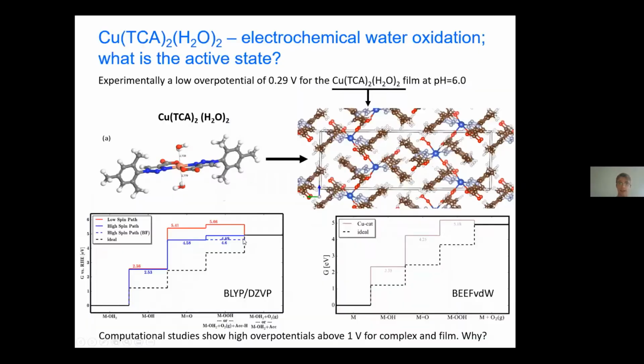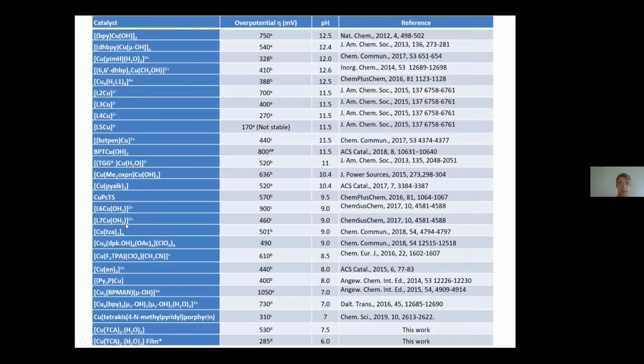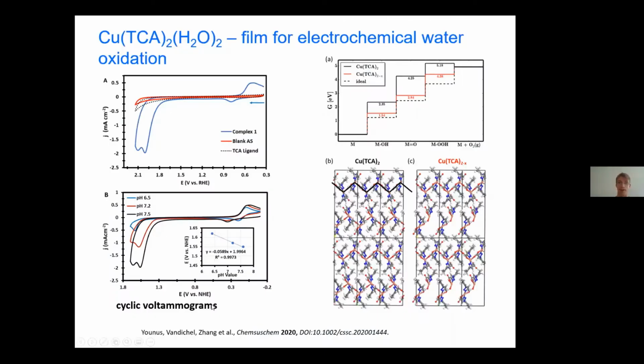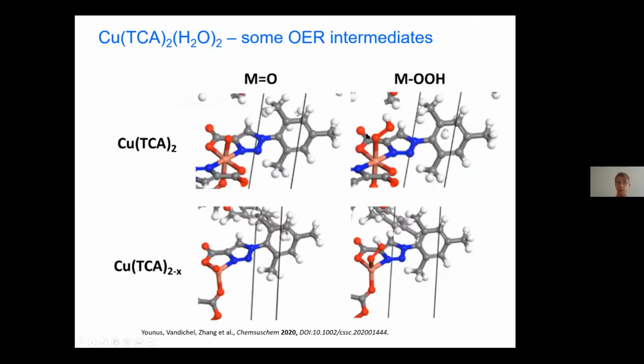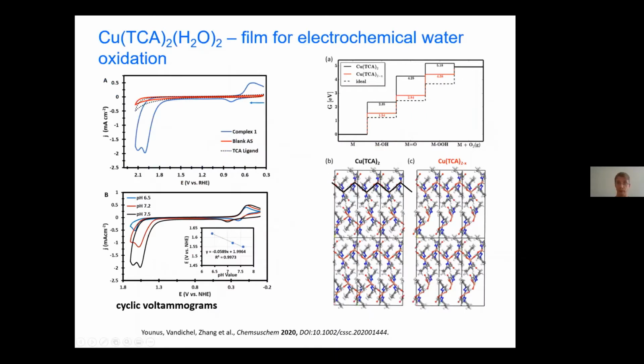So totally not corresponding with the low overpotential observed experimentally. So that means experimentally something else must happen. And you see here that these copper complexes from this study were among the best, so at quite low pH, achieving a very low overpotential for this film is quite surprising, actually. Why is that? So maybe it's because defects are formed within this copper TCA film. Because if I calculate the different steps in the catalytic cycle on a defective system, I obtain a much lower overpotential. That is more in line with experiment. So that could potentially explain why this film is active and has such a low overpotential for OER.